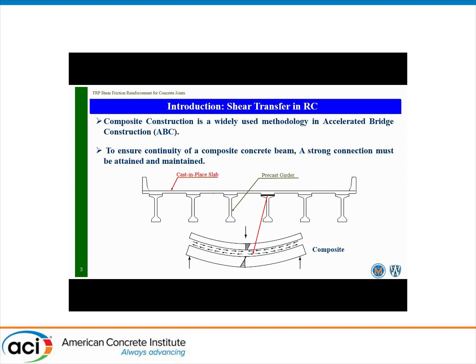Accelerated bridge construction is a very famous approach for bridge construction, and the most adopted system is the girder-slab type, using pre-cast, pre-stressed girders with cast-in-place concrete slab. To get the best out of the system, we need the girder to be composite with the deck slab, ensuring compatibility and composite action, which requires the full transfer of longitudinal shear between the deck and the girder.